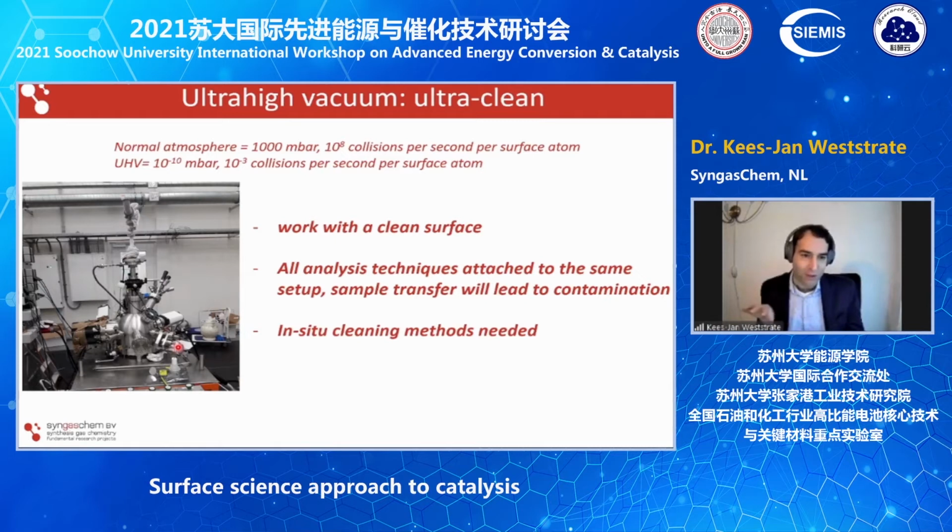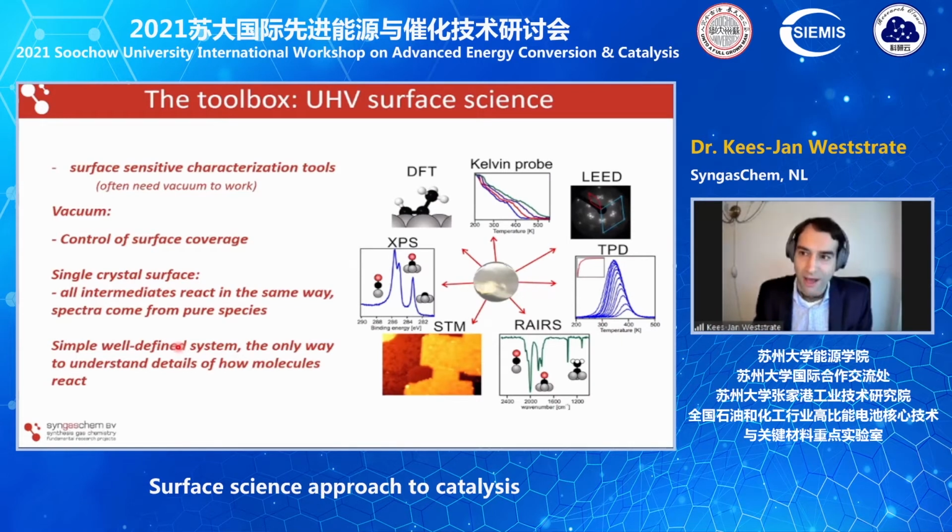And you need to have all of them connected to the same vacuum vessel, because when your sample is clean, you need special in situ cleaning procedures for this. When it is clean, you cannot simply take it out and analyze it somewhere else, because you have to go to air and you will contaminate it. And then when you have this, you can use a number of analysis techniques that give you information about the surface of this beautiful single crystal